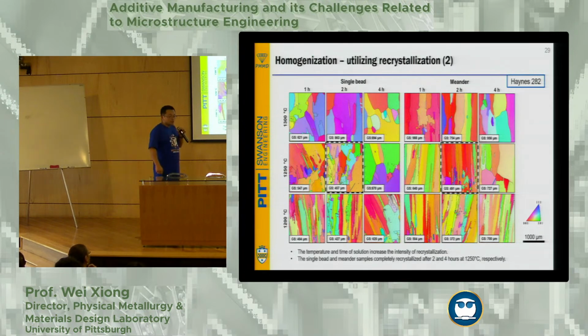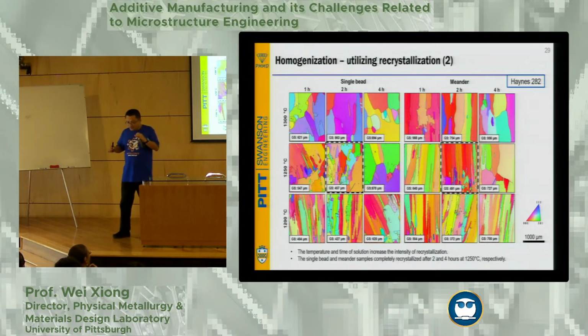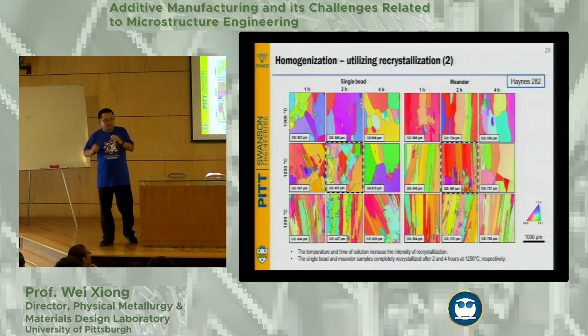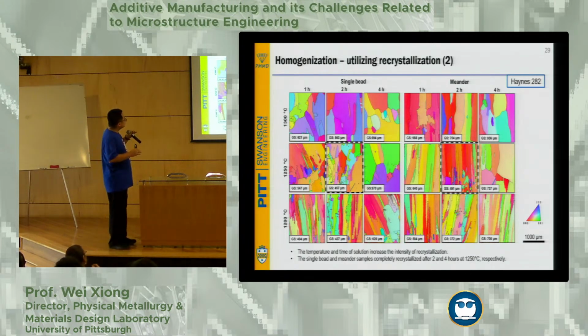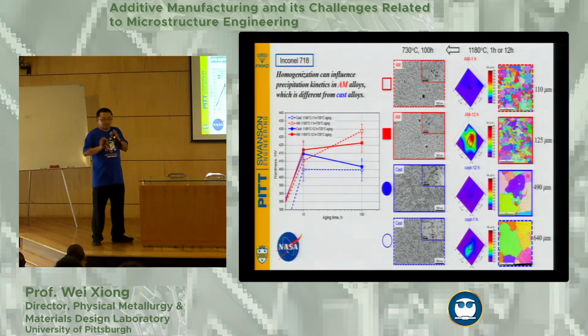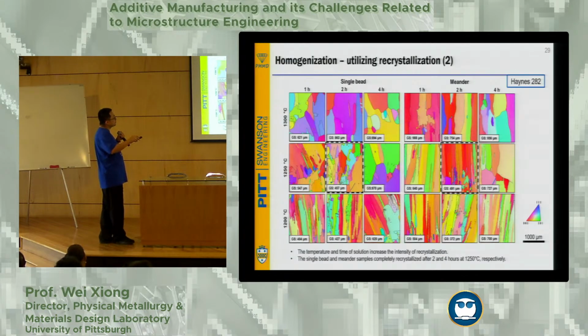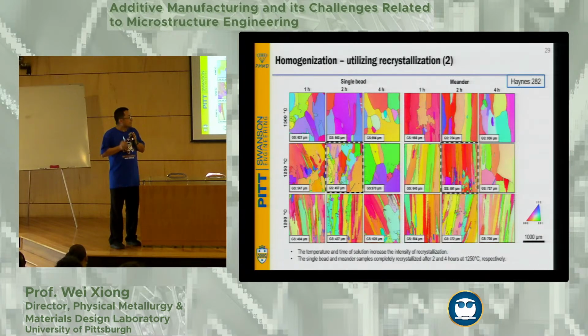So with this study, we learn a little bit about the grain structure. That's very important. And then we want to look at an even more challenging problem with Haynes 282. As I said, this is a laser powder bed fusion process, and the structure is actually much finer. If you do the wire feed process with Haynes 282, that's wire feeding with welding, these columnar structures are talking about even more than 1 millimeter. You don't want this at all.